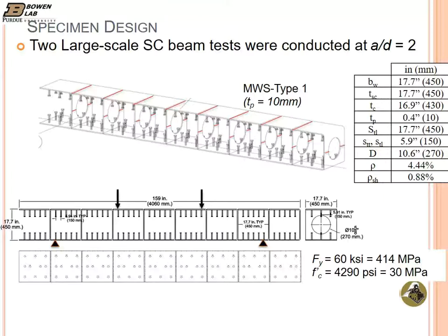And you may realize it's a very high number, 0.88% shear reinforcement ratio. That's very high because of having the inner plate being equal thickness with the faceplate. And we wanted to test it to fail it in shear, which was quite hard with this high shear reinforcement ratio. So we went with the lowest aspect ratio, which is the shear span to depth ratio. That's the shear span from load to support, that distance versus the depth. So the lowest we could go was 2.0.